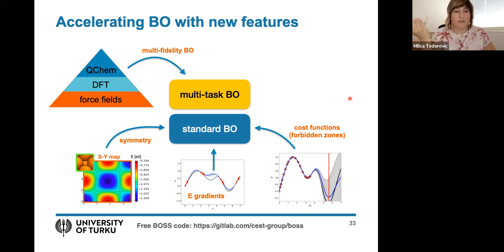Another method that we were very keen on is minima hopping, because of course it's really exhaustive. You're guaranteed to find a solution. But that method does too many relaxations for us. So it hops and then it relaxes, and then it hops and then it does a structural optimization. And you do a lot of these DFT steps in structural optimizations. Every time you hop, it's random, and then you might not be starting from a good geometry and you might take many steps to relax.